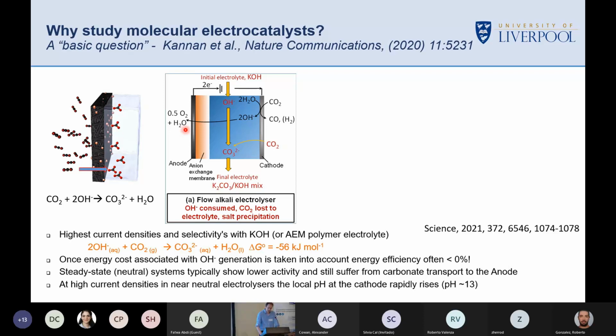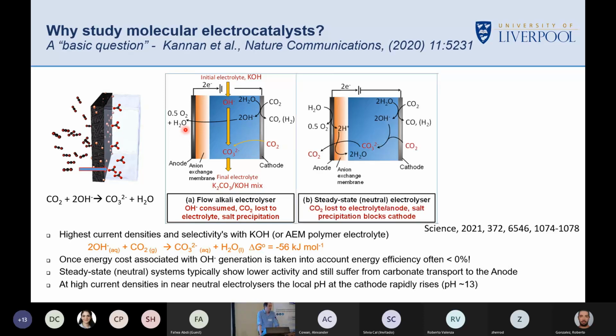That's a big cost. We can, of course, go near neutral, so we could use a bicarbonate-based electrolyte so that we can get a steady state near neutral operation. That's fine. We're still going to lose some of our CO2. It might not be quite as bad. We're likely to lose some of the Faradaic efficiency. And we have a secondary problem as well that we need to be aware of, that these carbonate salts and bicarbonate salts can actually form in the pores of the gas diffusion electrode.